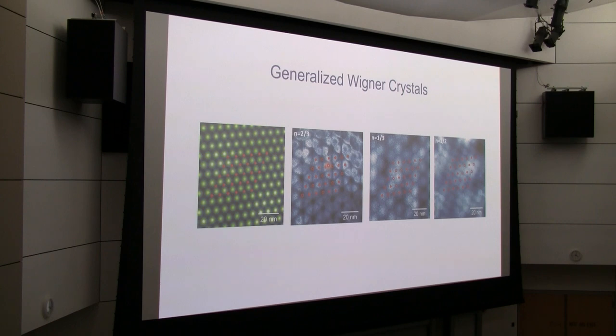And when we change the density to 1/3, you can see, again, you indeed have a 1/3 filled generalized Wigner crystal state where all the nearby sites are empty. We can also see a state at 1/2 filling. In this case, they actually spontaneously form a stripe phase. So it breaks the rotational symmetry in the system.